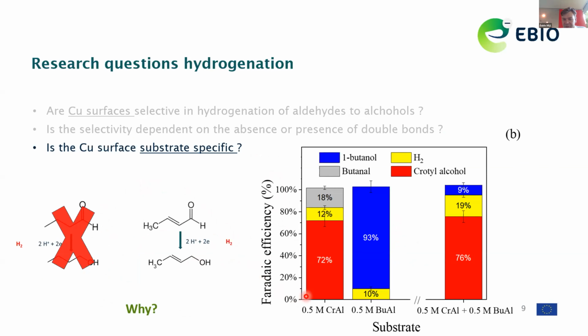And what the result shows you is clear here. So this is just to remind you the crotonaldehyde by itself. Here you see the result at half a molar of butyraldehyde that I also showed you already. And here is the result of the combination of half a molar crotonaldehyde and half a molar of butyraldehyde. And then what you see is that the product distribution is very similar to what we actually obtained with crotonaldehyde alone. So this shows you that the surface specificity for the double bonded aldehyde is very high for the copper